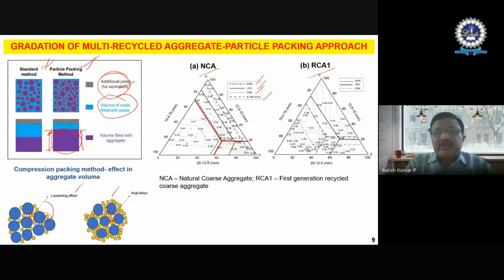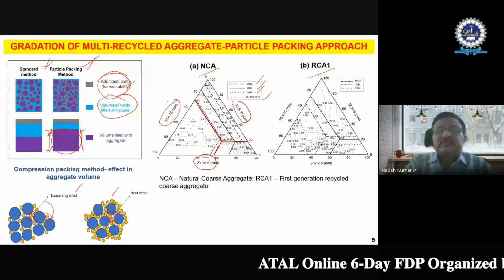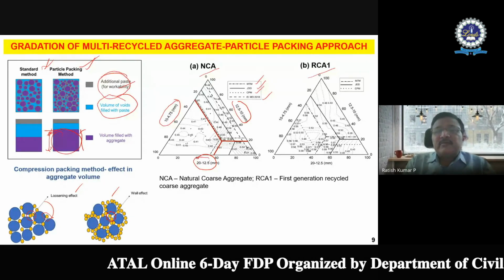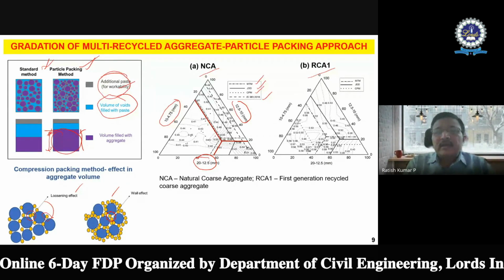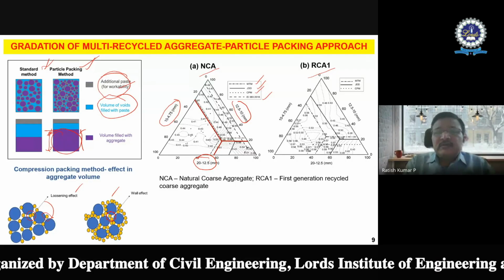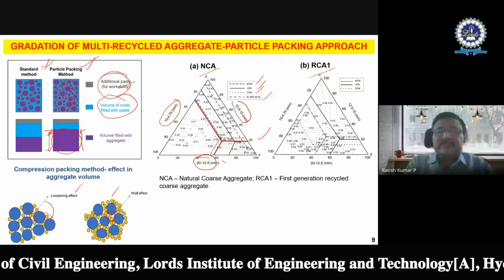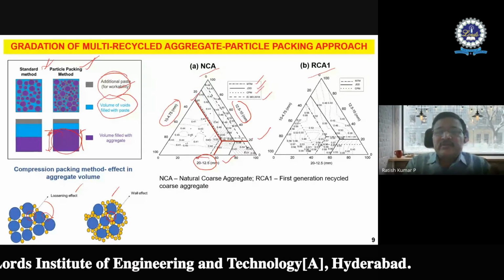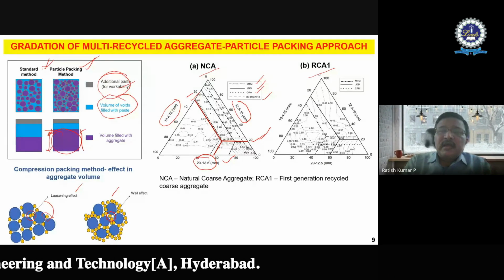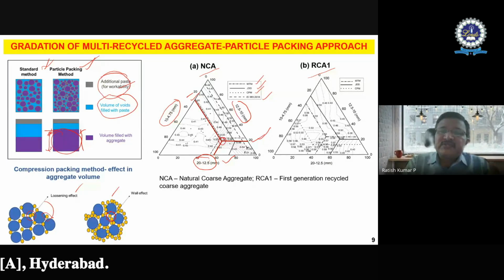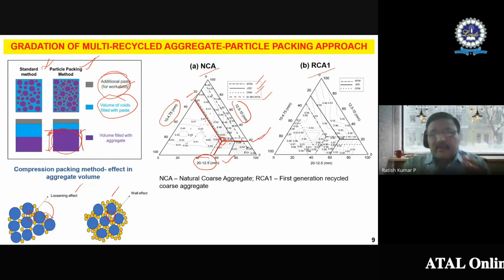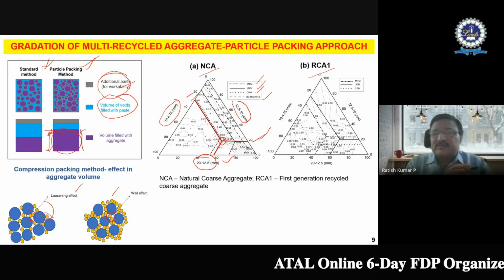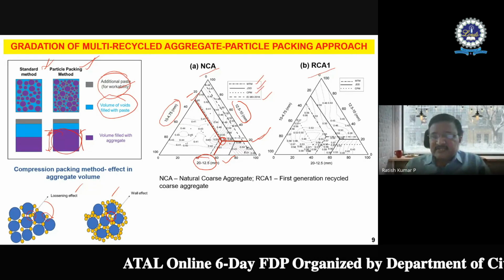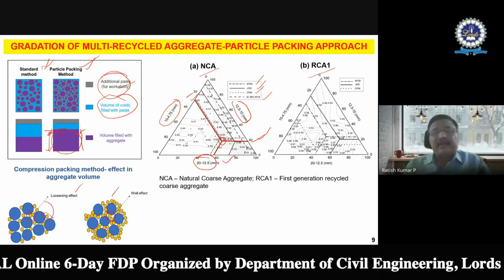We have 20 to 12.5, we have 12.5 to 10, and we have 10 to 4.75, and then we get a combination of different values, right? 20% of this one, 60% of this one, and something like 20 to 28% of this one. And then there is a certain point where there is an intersection, which is a point where you get the maximum density or maximum packing you are going to approach. That's called maximum density or maximum packing or particle packing.